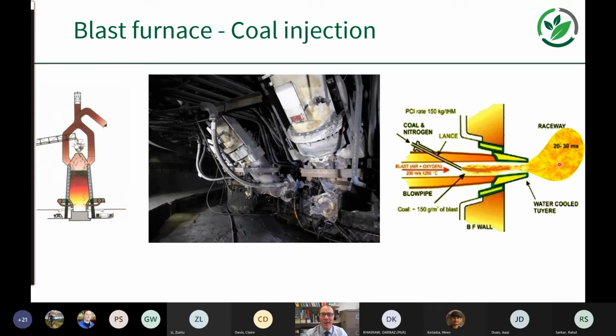And the raceway is where sometimes you've got enriched oxygen which is injected into the furnace, and this is where the temperature really ramps up and combustion or partial combustion takes place. So you get heat generation, you get the production of carbon monoxide, which is the main reducing gas in the process. You also get production of a certain percentage of hydrogen depending on the type of coal that you're using as well.